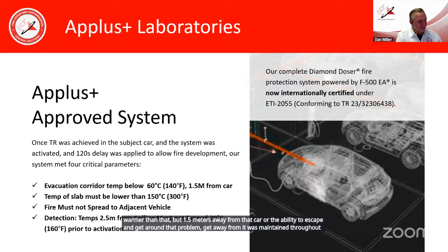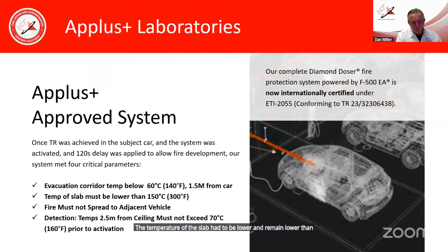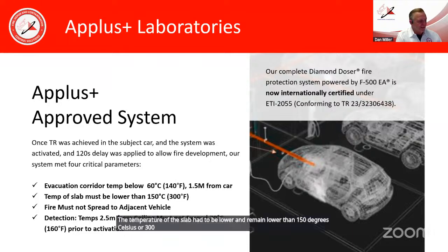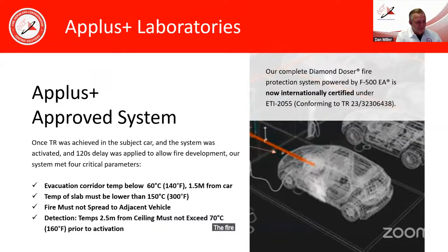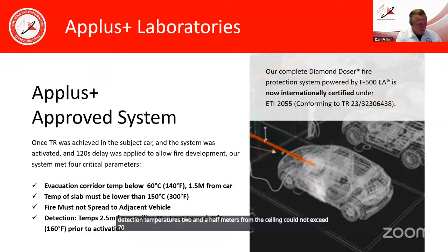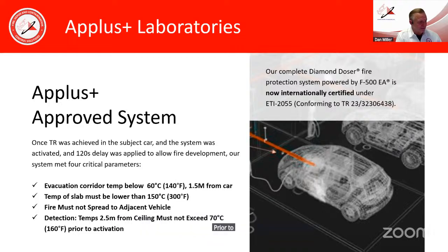The temperature of the slab had to remain lower than 150 degrees Celsius or 300 degrees Fahrenheit. The fire could not spread to the adjacent vehicle, and it did not. And the detection temperatures, 2.5 meters from the ceiling, could not exceed 70 degrees Celsius or 160 degrees Fahrenheit prior to activation, and they did not.